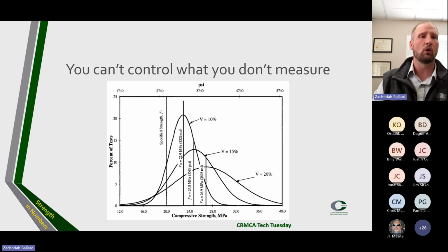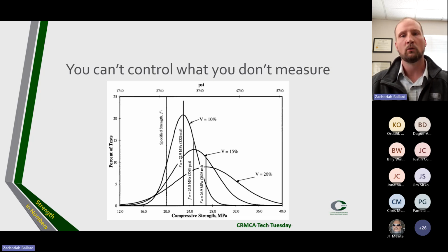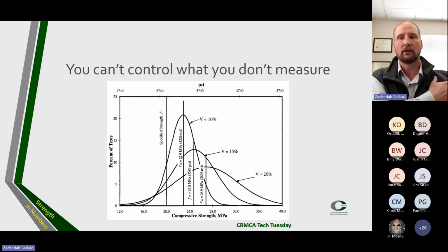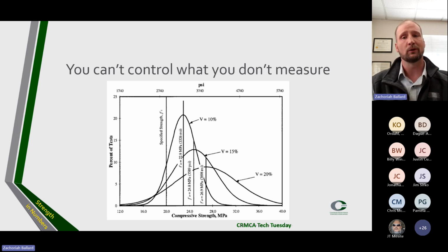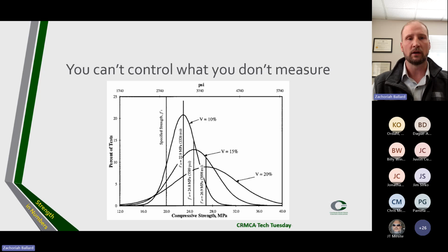So we can't control what we don't measure. We'll use compressive strength as an example. We all generally test and track compressive strength. And this can be done, and maybe should be done, with some other parameters as well, like shrinkage or permeability through surface resistivity or RCP, maybe rheology or stickiness. But our normal distribution of test results gives all of the test results possible depending on a coefficient of variation.